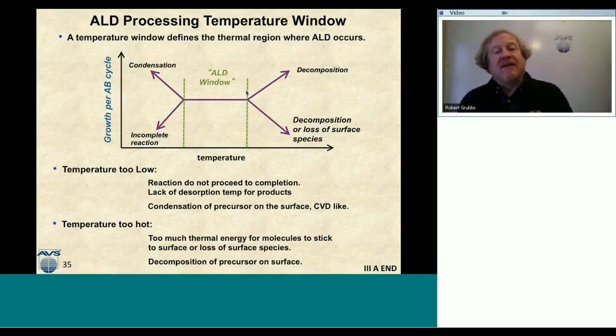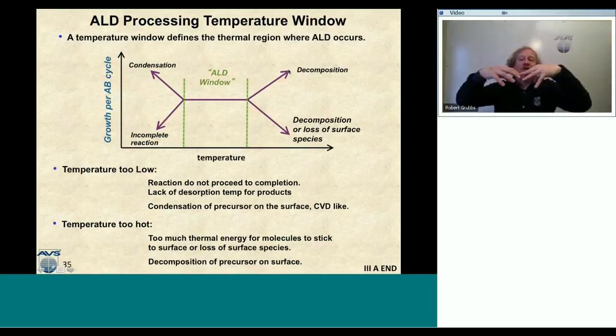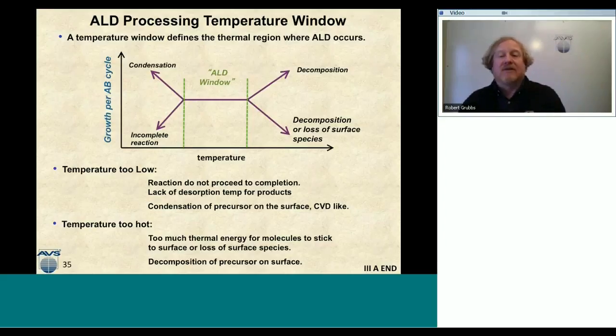Now the same exists with being too hot. Now I mentioned in the CVD that we can make our sample very, very hot, be in the mass transport limited regime, and every molecule that goes in is going to react on that surface. But in ALD, if we're too hot of a surface, our precursor molecule can come down on the surface, decompose, and sort of poison our surface, or we actually just start to build a multilayer of decomposed products on the surface as I do my AB cycles. And that's when the temperature is too hot. Or I can decompose and then I just sort of desorb all my surface species from the surface.